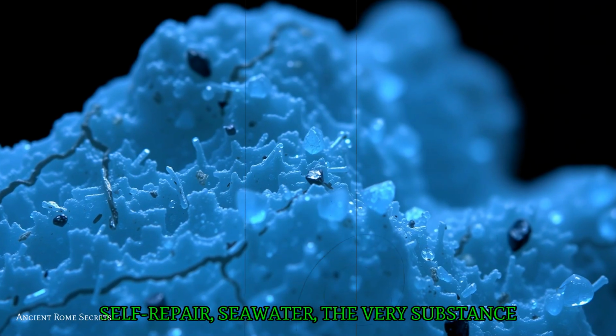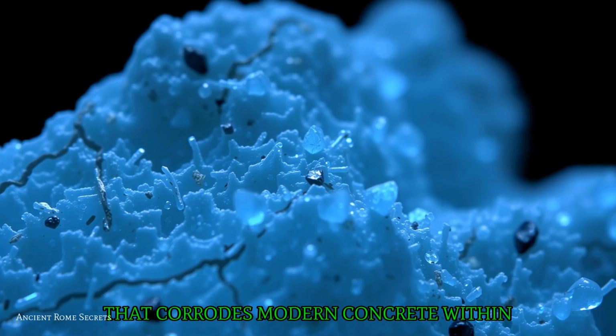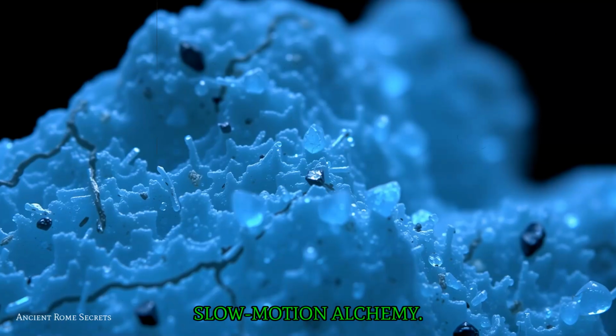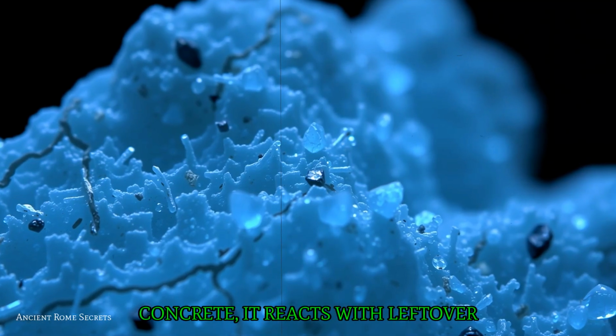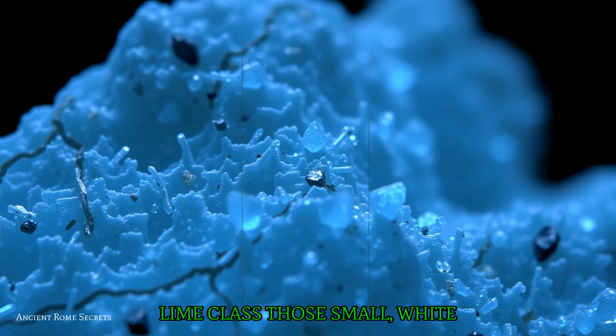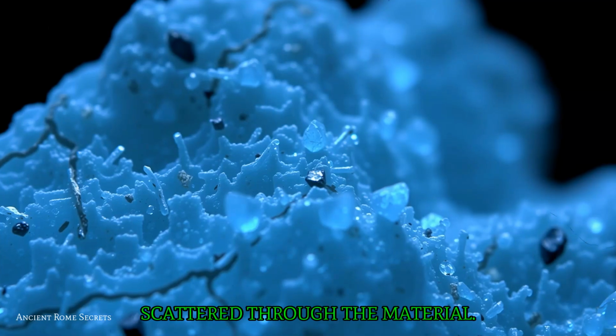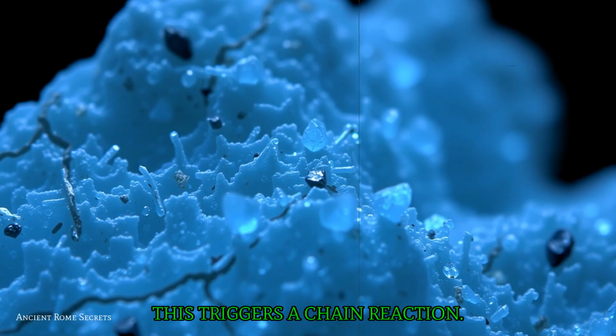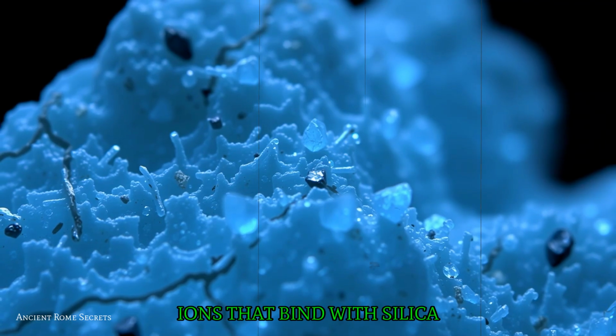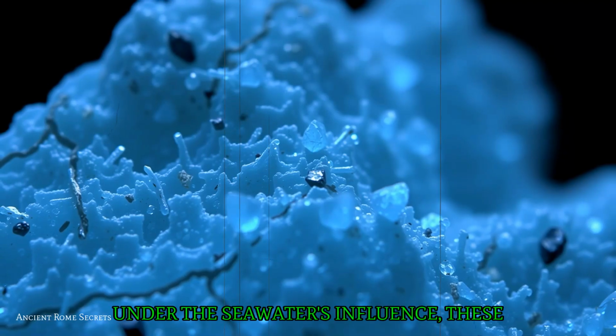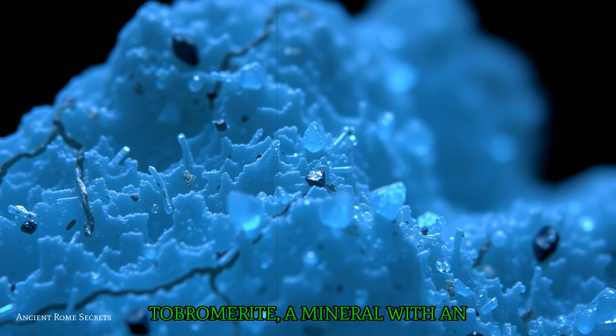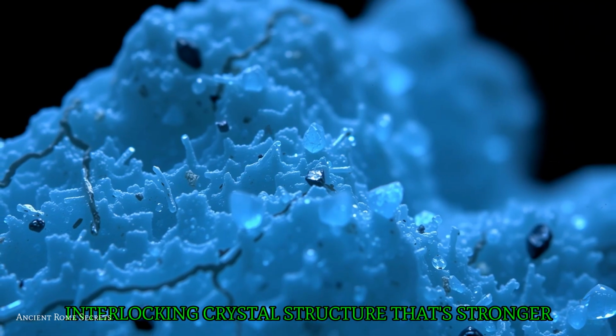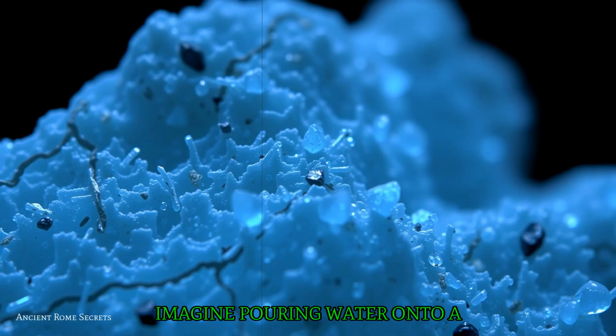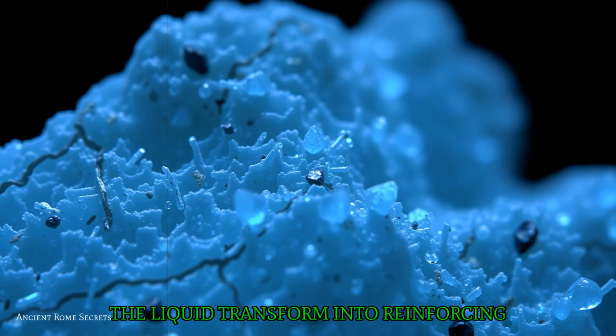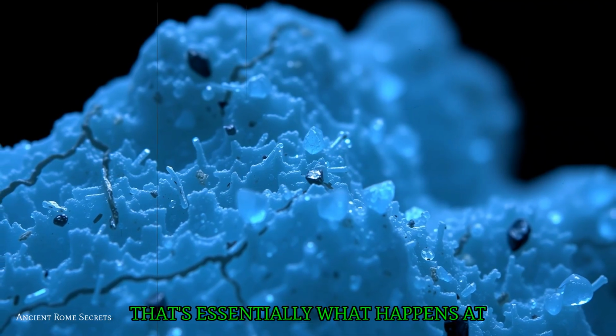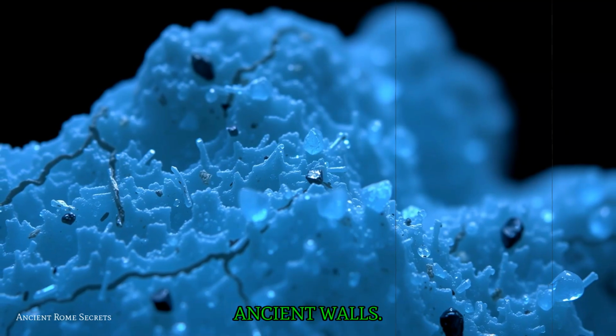And the catalyst for this self-repair, seawater, the very substance that corrodes modern concrete within years. The process works like a slow-motion alchemy. When seawater seeps into Roman concrete, it reacts with leftover lime clasts, those small, white flecks of unreacted calcium hydroxide scattered through the material. This triggers a chain reaction. The lime dissolves, releasing calcium ions that bind with silica from the volcanic ash. Under the seawater's influence, these elements reorganize into aluminous tobermorite, a mineral with an interlocking crystal structure that's stronger than the original binder. Imagine pouring water onto a cracked sponge, only to watch the liquid transform into reinforcing fibers that knit the gaps together. That's essentially what happens at a microscopic level in these ancient walls.